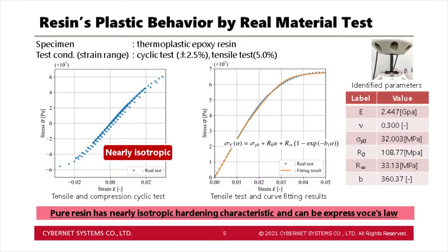Here is a stress-strain curve for pure resin. In this study, a thermoplastic epoxy resin was used as a matrix. The graph at the left-hand side is the results of the cyclic loading test. We focused on the yield stress on the tensile and compressive side. It was determined here that the hardening behavior is almost isotropic. So only the properties of the tensile side were used to identify the material properties of the resin. The result is shown in the graph on the right.